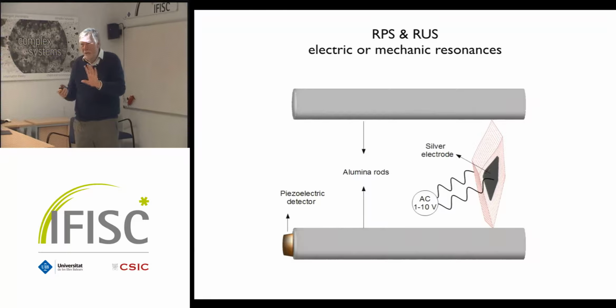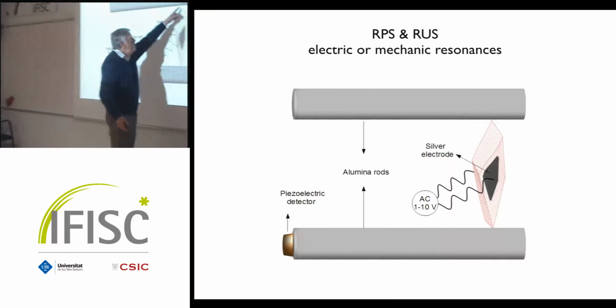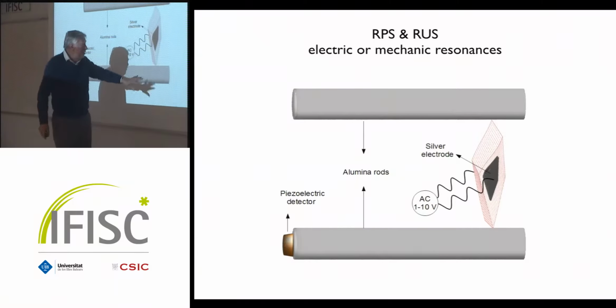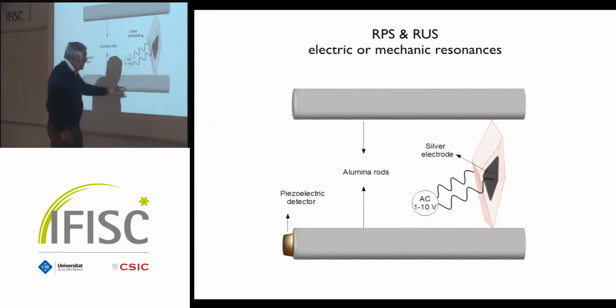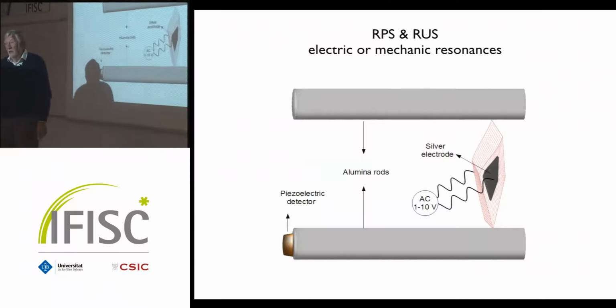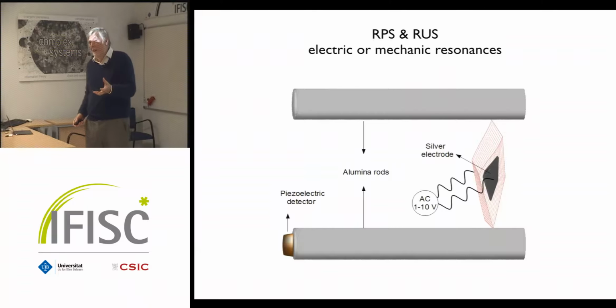So not ferroelectric or something dramatic. Now, if there are domain boundaries which are polar, what do you do? You shift them around. You swing them from right to left. So then, you can't measure that, of course. I mean, in an electron microscope or so, you can't do that. But what you can do is the emitted sound. You move them forwards and backwards, and then you measure at these two ends, you put some sticks on there. I mean, these are ceramic sticks. And then you put at the end of the stick a microphone. Well, it's a glorified microphone. It's a very expensive microphone, but it's still a microphone.